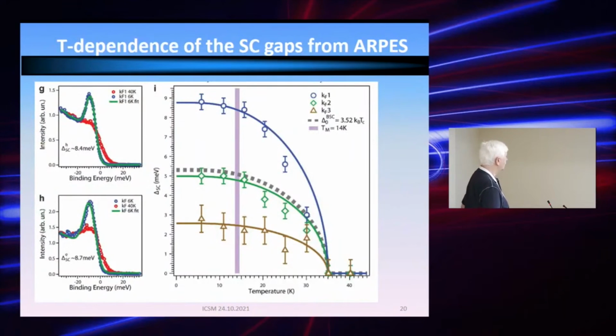So according to this data, the largest gap develops on the largest hole barrel. Is it right? The large gap belongs to the electron pocket at the M point, and as far as I remember, the inner cylinder. And the smaller gap belongs to the two other cylinders. So actually, the order is the same as in the 122 material.